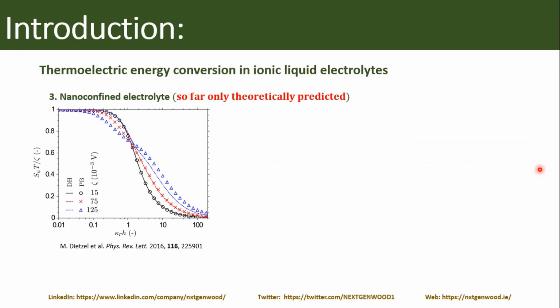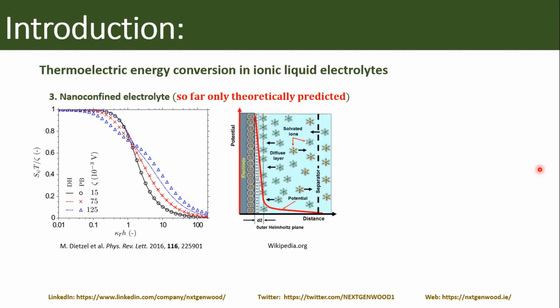So what they did is they decided to study the effect of an electric field on this Soret effect. And the idea they had is that if you have this electrolyte and place it inside of a nanochannel, we know that when we have contact between liquid and solid, on the surface we create an electric double layer, which results in formation of a surface charge. And so if we have a nanochannel which has a characteristic size comparable to the width of this electric double layer, then the whole volume inside of the nanochannel is charged. And so if we place our ions in this electric field, we can see significant deviation from the bulk behavior.